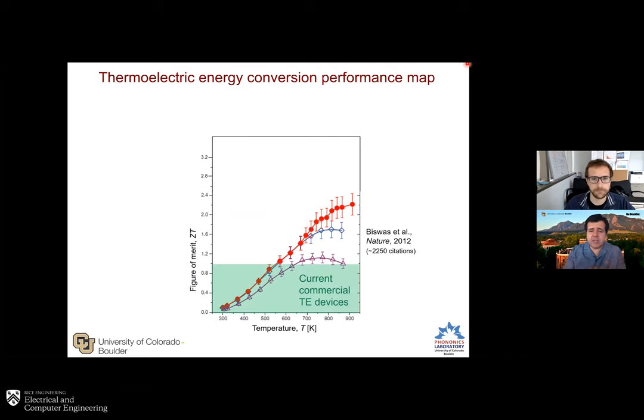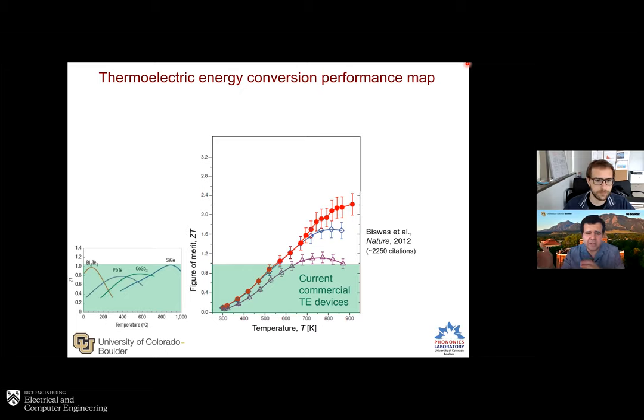So to put things in context, as far as commercial thermoelectric devices are concerned, they tend to be hovering around that green region. So the performance tends to be limited to roughly one. And these are a few examples. Each type tends to peak at a certain temperature. So you've got bismuth telluride, for example, lead telluride, silicon germanium at high temperatures, and so on. It's also interesting to look in this picture at a very common material like silicon. It would be intriguing to see if silicon can be used as a base material for thermoelectricity, because of course it's very abundant and it's been widely used in the electronic industry, has good mechanical properties and so on.